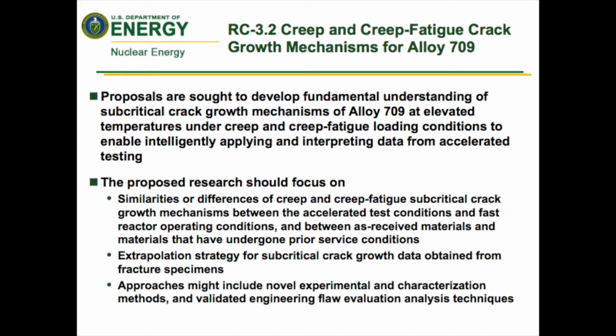There was an extensive wide funnel that we looked at lots of different materials, 1 ferritic and 1 austenitic material, and we wanted to look for ones that had higher creep strength primarily, but without sacrificing the other properties, things like weldability, ductility, fracture resistance, microstructural stability, et cetera, et cetera. And it turns out that after several years of study and down select, among the austenitic alloys, 709 came out on top. Sam, you got anything to add to that?